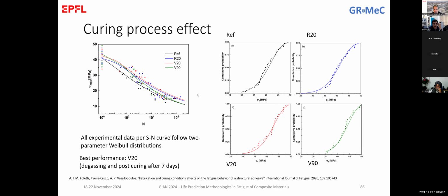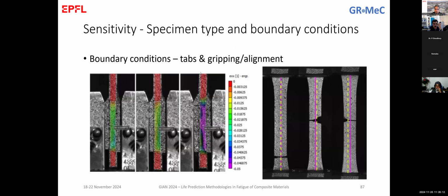We've seen that the post-curing helps when it is not immediately after mixing. So the green one is the V90. You remember V90, we mixed and then we post-cured directly. And this seems not so beneficial as the performance of these red ones, where we mixed, we let the material cure at room temperature, and then we post-cured after these 7 days. So the best performance that we investigated for these materials is the one given by these V20 specimens.